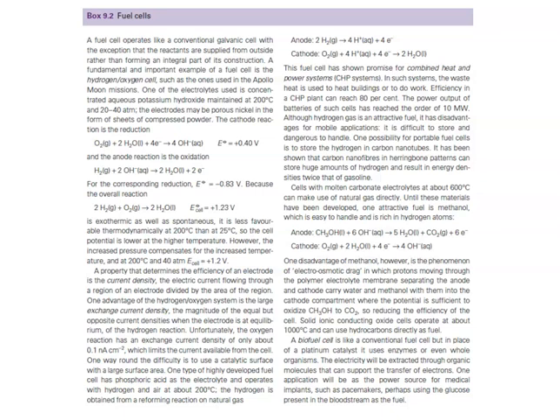Apollo moon missions. One of the electrolytes used is concentrated aqueous potassium hydroxide maintained at 200 degrees Celsius and 20 to 40 atmospheres. The electrodes may be porous nickel in the form of sheets of compressed powder. The cathode reaction is the reduction of oxygen gas plus two waters plus four electrons, yielding four hydroxides with a reduction potential of plus 0.4 volts. And the anode reaction is the oxidation of hydrogen gas plus two hydroxides, yields two waters plus two electrons, and it has a corresponding reduction potential of negative 0.83 volts.